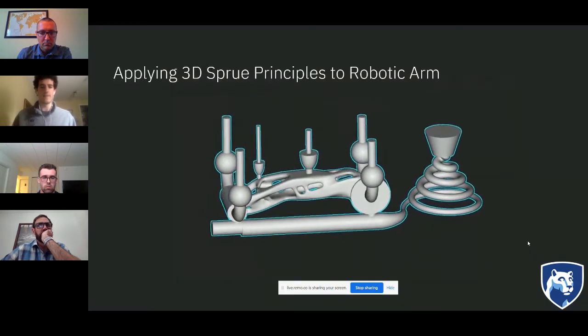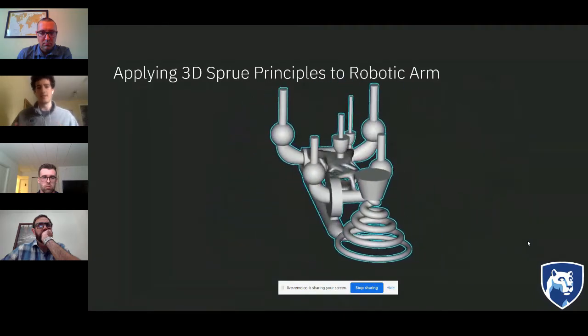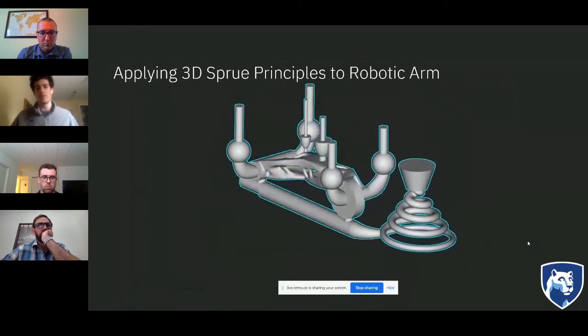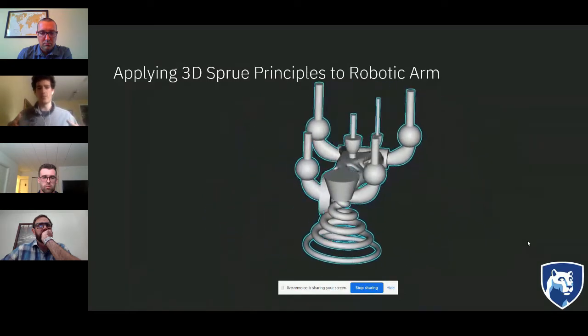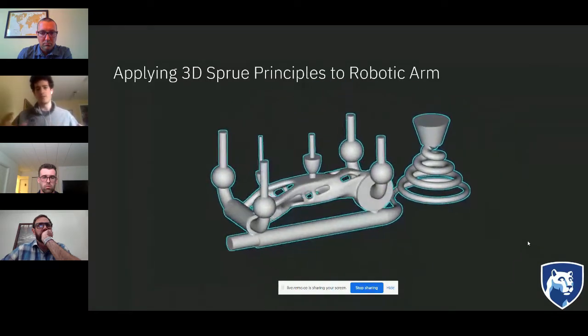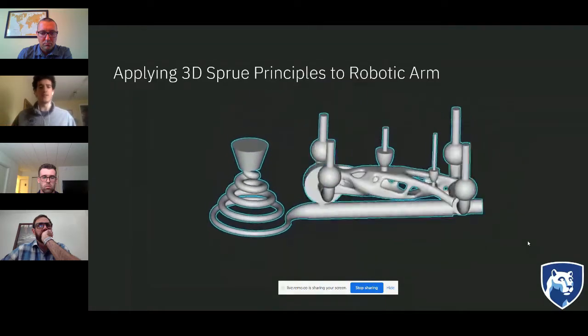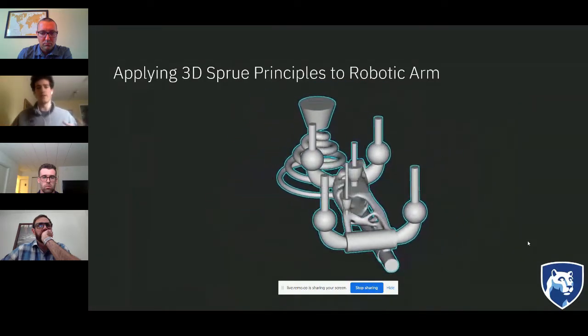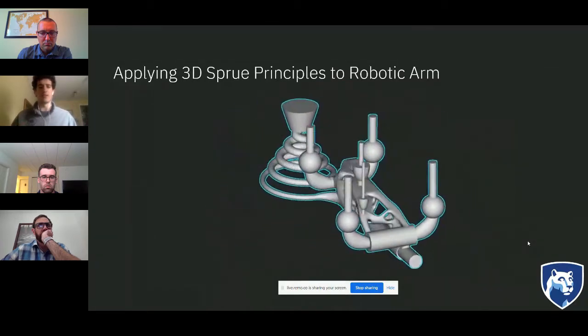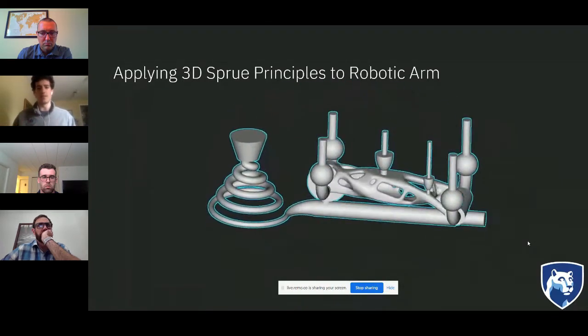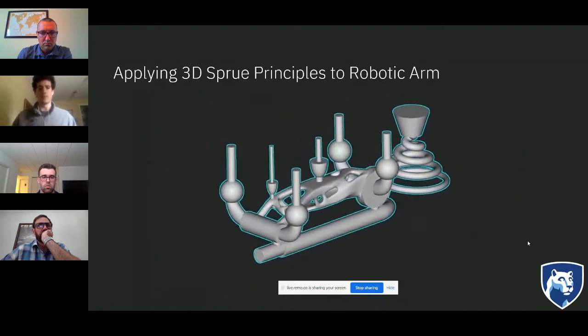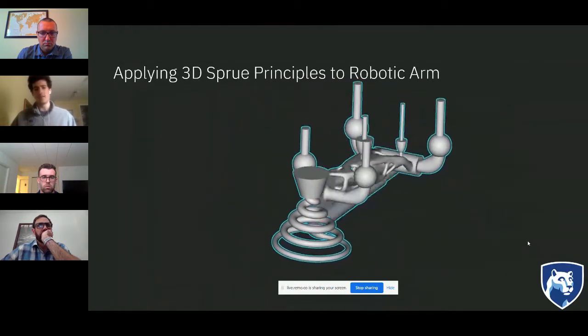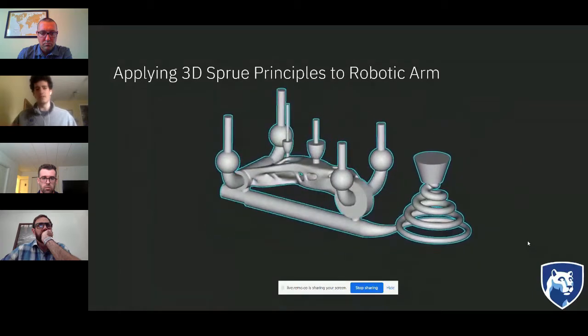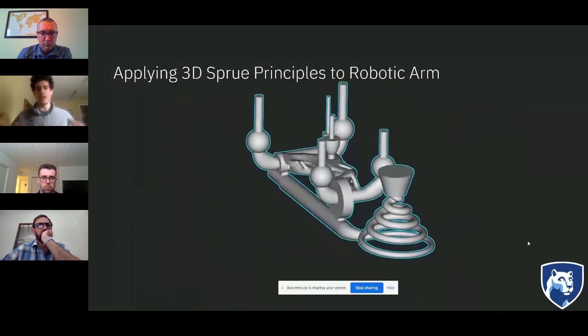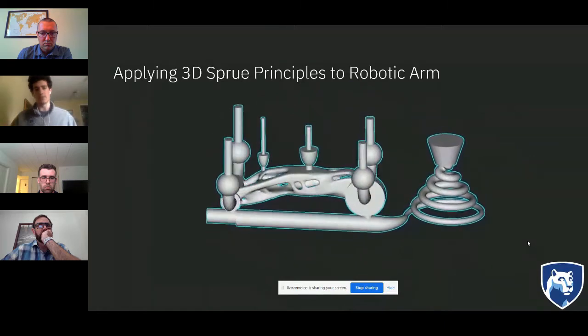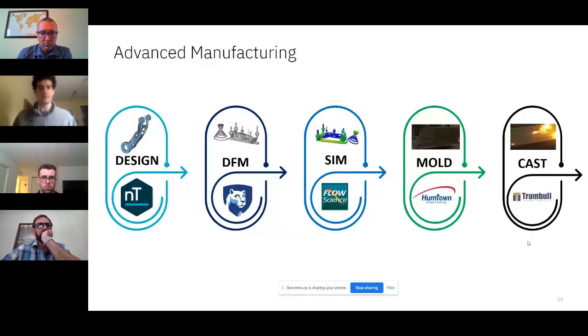Next slide, please. And so here again is the picture of the final product that we came up with, which has a conical helix sprue on one side and then this long runner. Our goal was to fill the casting evenly, and I'll go into in the next couple slides about how when we were working with Flow 3D, looking at the simulations, iterating through that, we'd see that we get uneven filling depending on where the sprue was, and eventually we figured out that the best way to evenly fill it is to have a slightly tapered runner and then have two gates on either end of the casting so it would fill slowly.